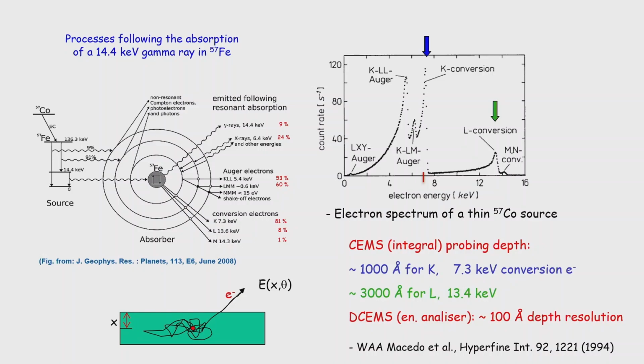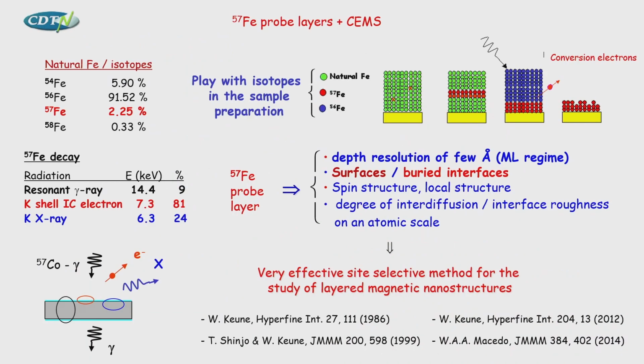If you use an analyzer to select part of this energy spectrum, by using an energy analyzer we get what we call depth selective conversion electron Mössbauer spectroscopy. Due to the process of energy loss, we can have not more than 100 angstroms depth resolution in this way. That means it's not very nano sensitive. But if you want a really nano resolution, we can play with the isotopes when we prepare our samples, as Kai has shown to us on Monday. Then we can have a resolution in the monolayer regime. You can be very surface sensitive, but you can also go to very buried interfaces, up to 3,000 angstroms deep.